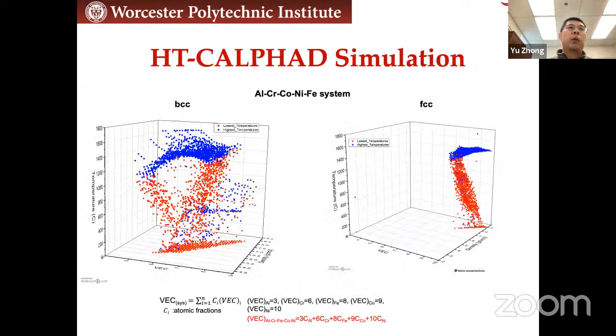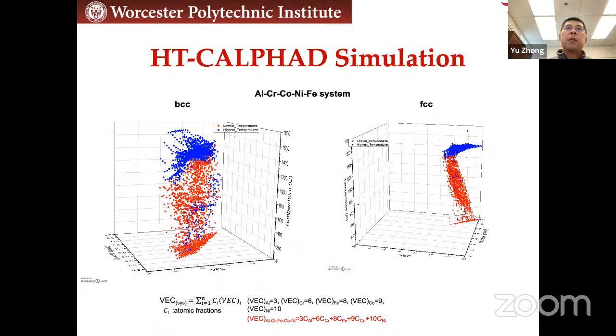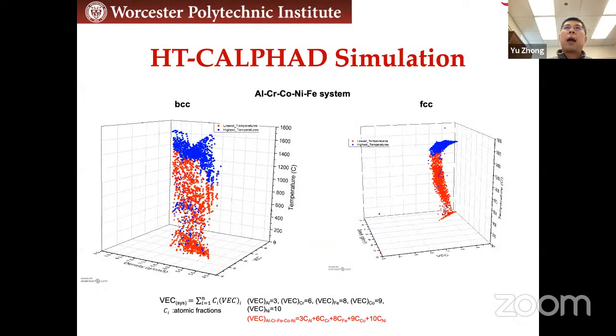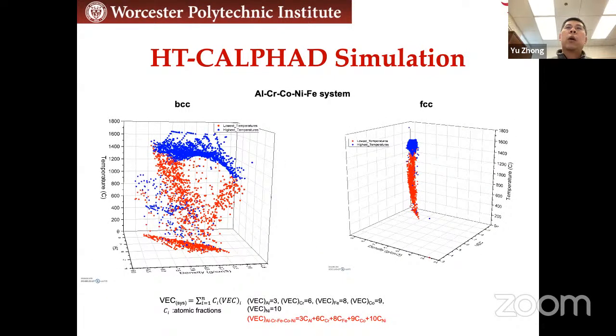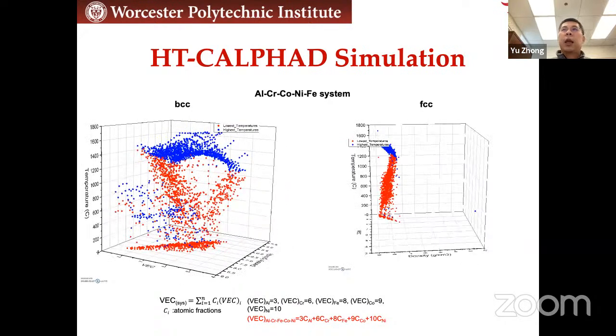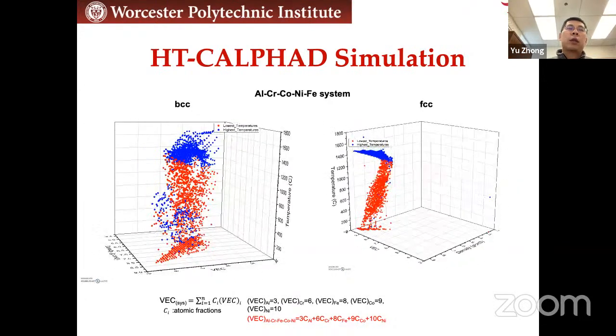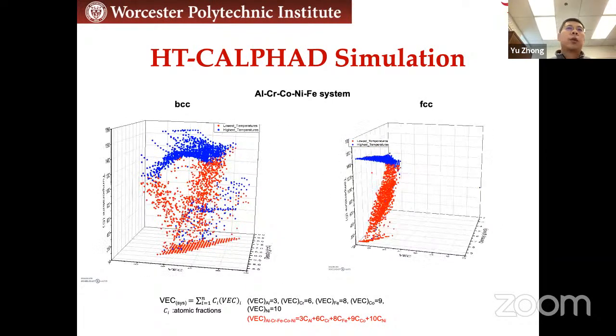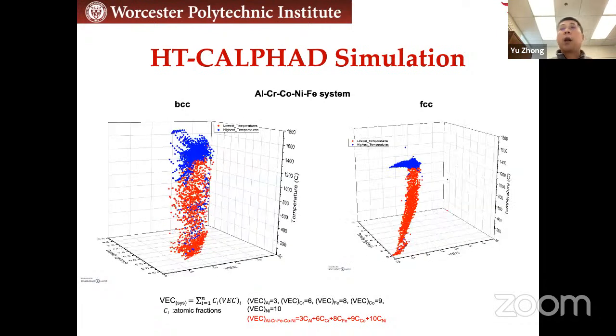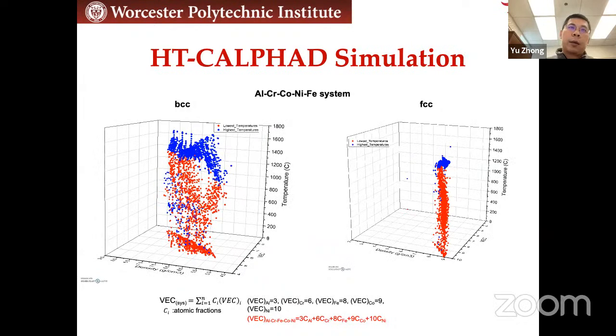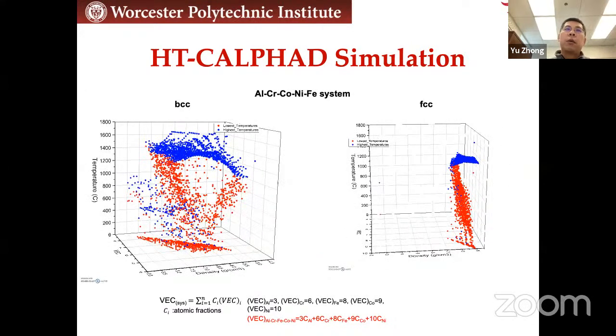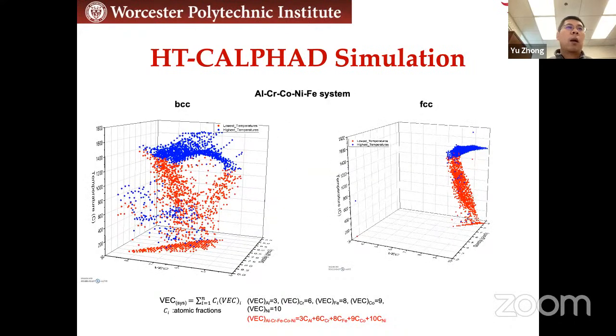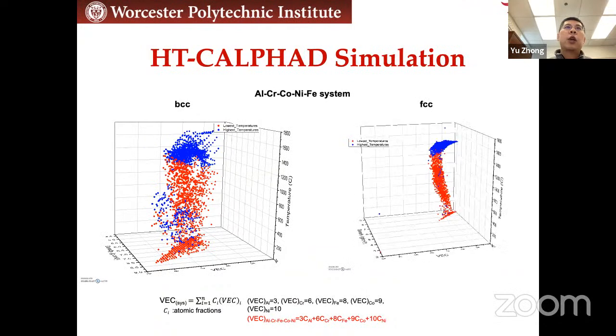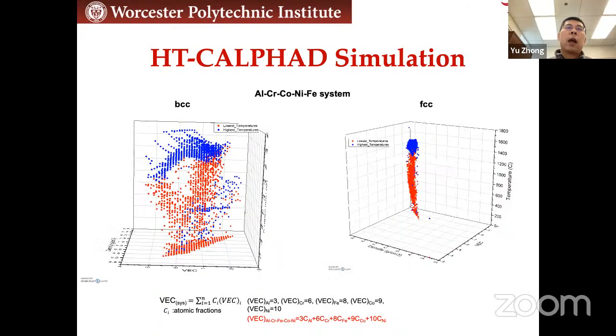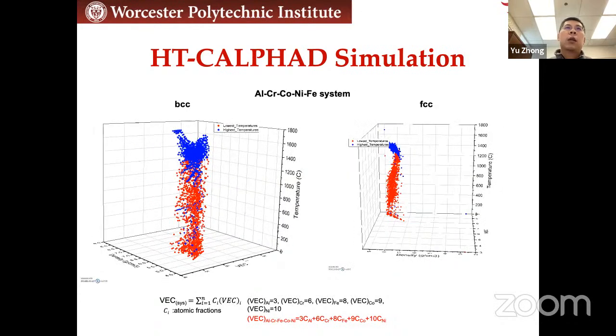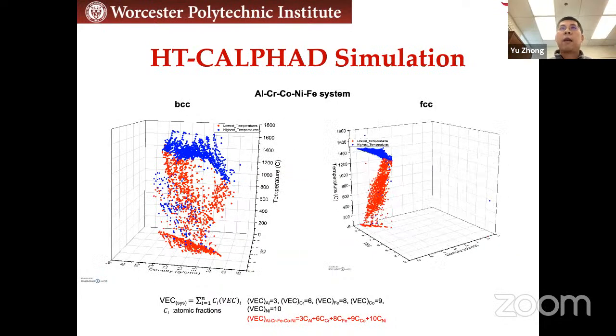The first one is about these high throughput calculations. These are the results we have for the aluminum, chromium, cobalt, nickel, iron 5-element system for the BCC and FCC, right? Instead of the traditional simulation where we do one simulation or two simulations, here we do several thousands of simulations. This is the result we got a couple of years ago. Now we can even do tens of thousands of calculations pretty quickly. But no matter what, this shows that high throughput calculations can be very efficient for getting the stability range for BCC and FCC.